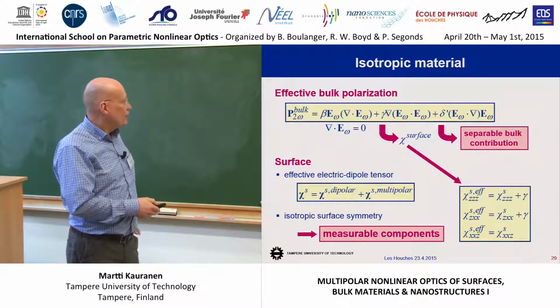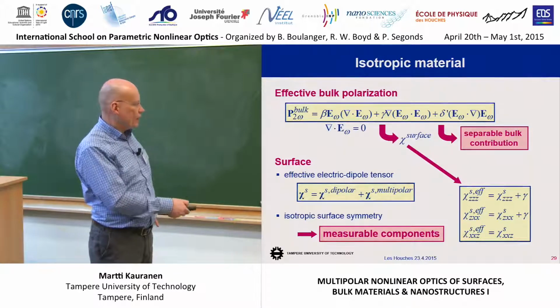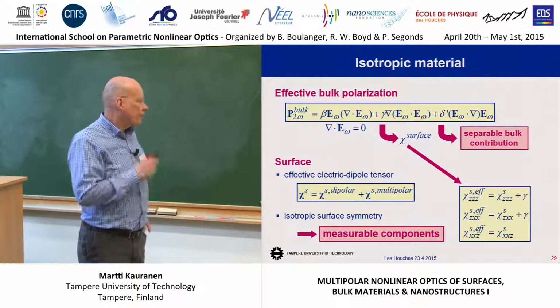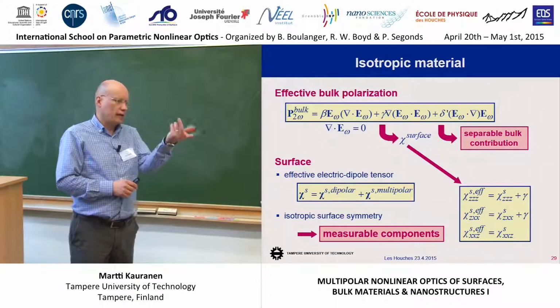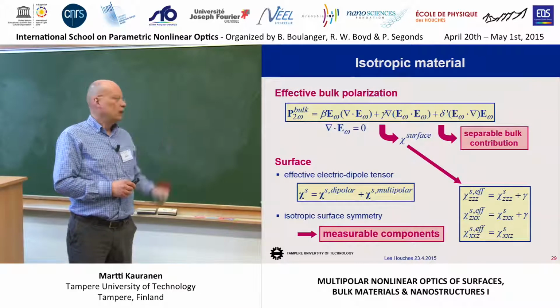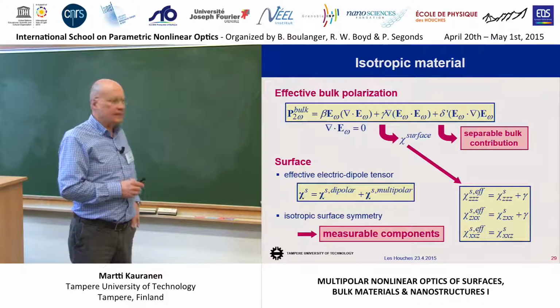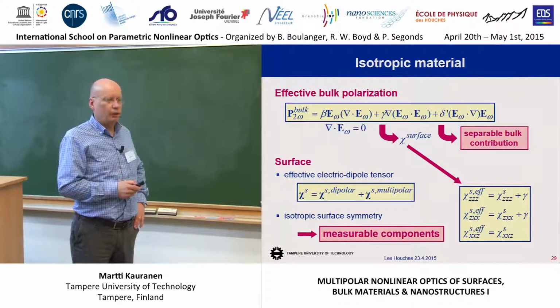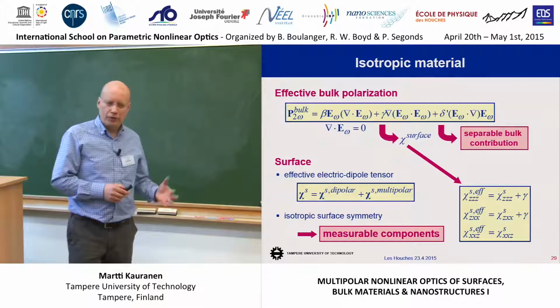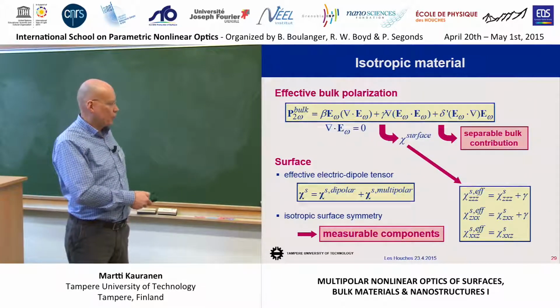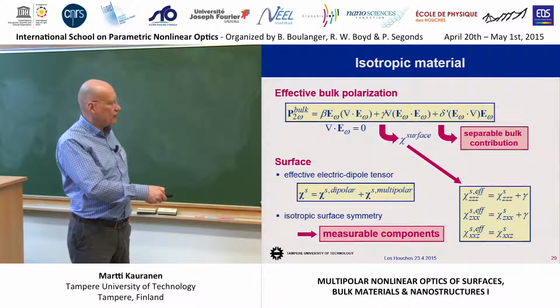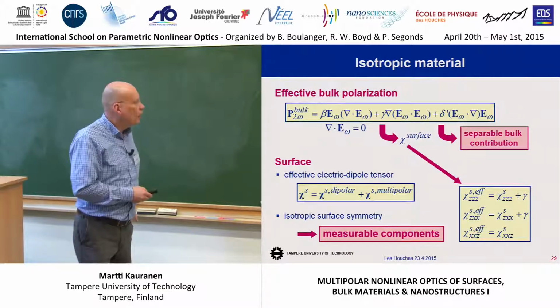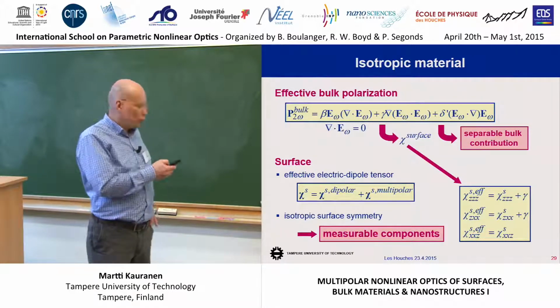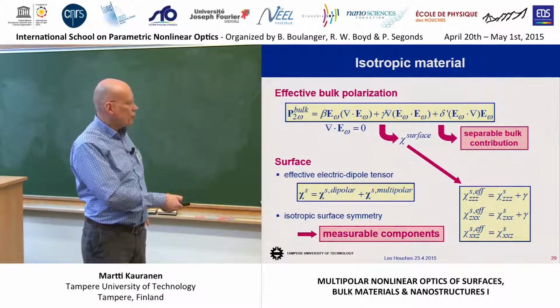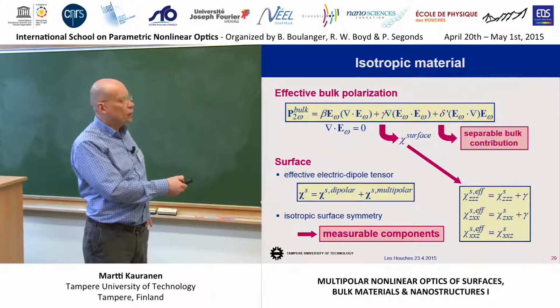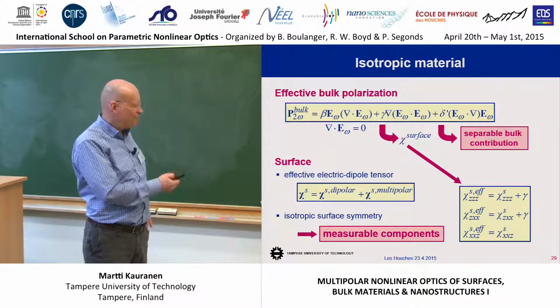And by the way, the fact that you have these components at the surface follows from the fact that you have a full rotational symmetry about the surface normal. Your symmetry group is C infinite V. And when you look at the tables and go through the operations yourself, this is what you find out. That you have three surface components. So in an experiment, we can try to measure these components and then this one bulk parameter. Okay?